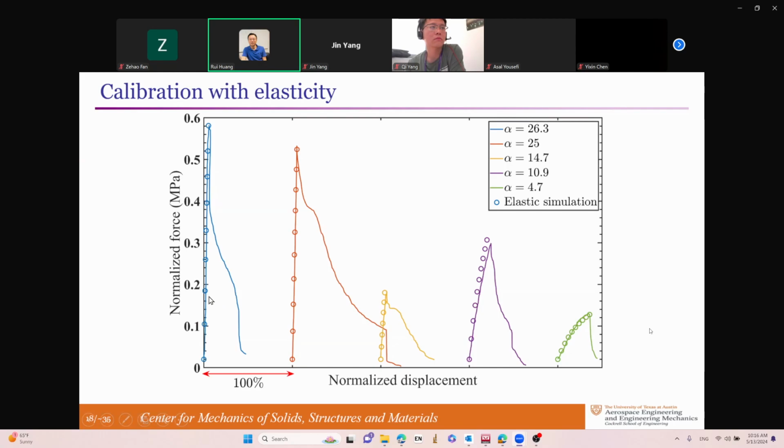This shows the nominal stress versus the normalized displacement of the entire gauge section as a function of the thickness. Thin specimens on the left side and thicker specimens as you go further. The thicker specimens exhibit a significantly nonlinear response. The underlying PDMS is a function of strain. The thinner specimens are so heavily constrained, they don't strain very much before the cavities pop. So they are almost linear up until the fracture initiation, nucleation.